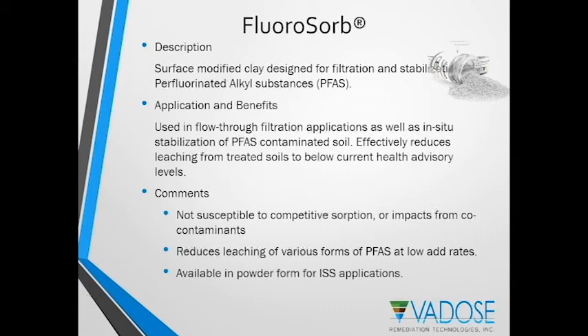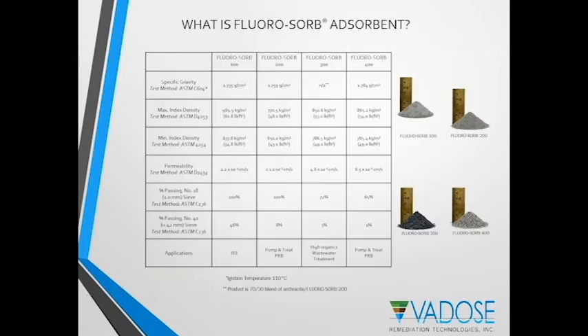Data has shown, which I'm going to present, that by adding FluoroSorb at very low rates can reduce the leaching of PFAS significantly to below the current health advisory levels. And this material too is available in a powdered form for in situ stabilization applications. This chart basically gives a range of the different products that are available. However, as we've mentioned, the first column here, FluoroSorb 100, is the one that would be typically used in in situ stabilization applications.